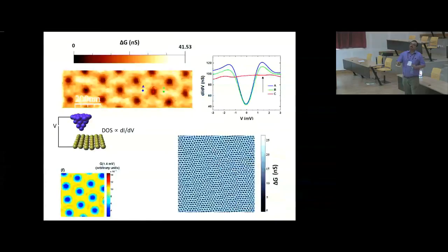All right, now how do we look at vortices? For vortices, we have this superconductor here, we have this tip here, and what we measure, instead of the tunneling current, is dI/dV through a modulation technique. Now, if you measure at this point A, for example, you see that dI/dV looks like this. This is typical of what you get in a superconductor. You have the coherence peak, and here you have the suppression due to the gap. If you measure at this point B, you see something similar, but when you have a vortex at point C, you see that it's completely flat because the vortex core is normal metal.